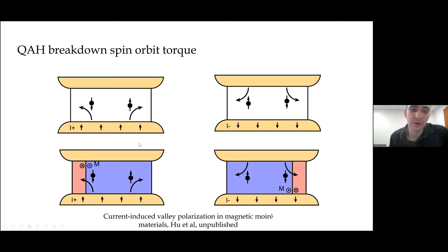And when that happens, you'll accumulate spin of opposite orientation on opposite sides of the device. On one side of the device, the spins will be happy. They'll be the same orientation as the background magnetization. But on the other side, they will exert a torque on the magnetization as they relax. Eventually, that torque will be so large that you'll locally flip the magnetization.